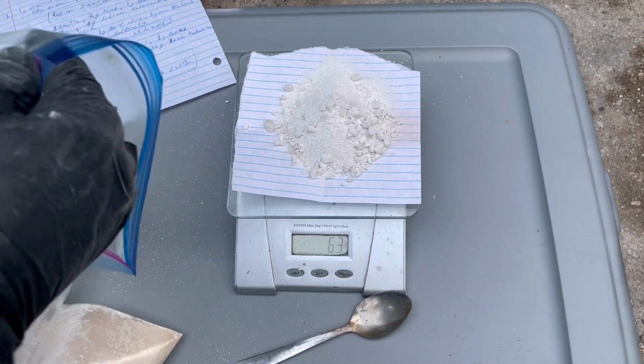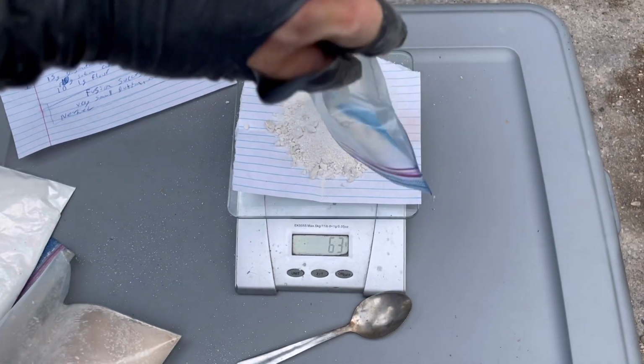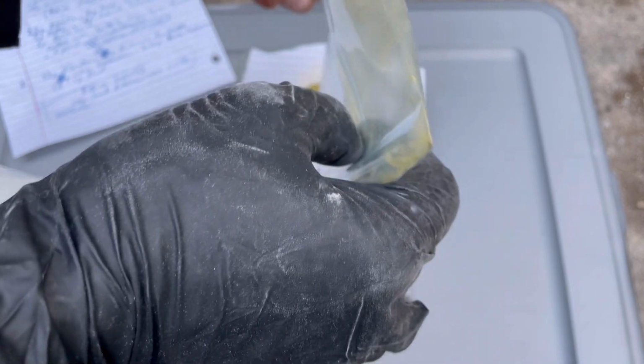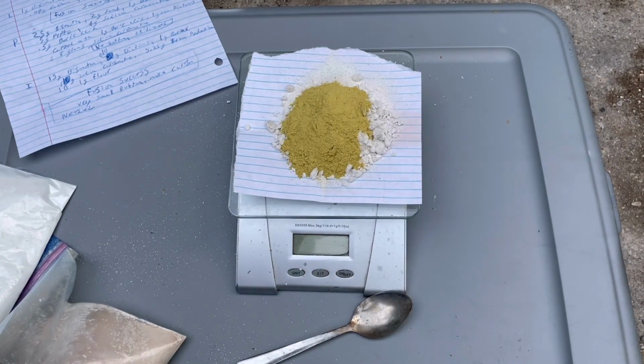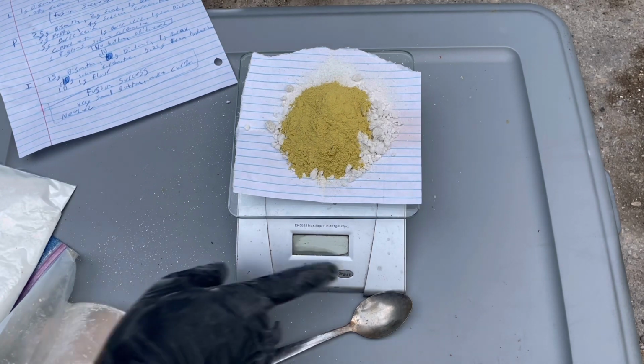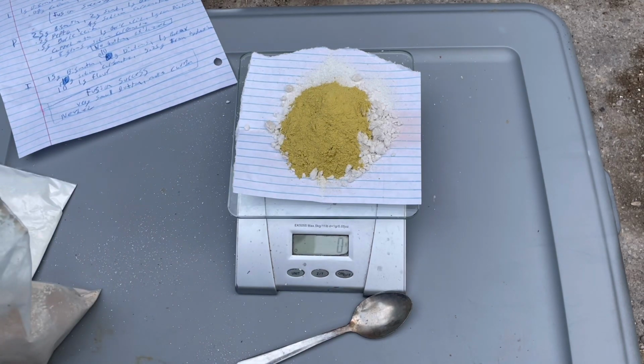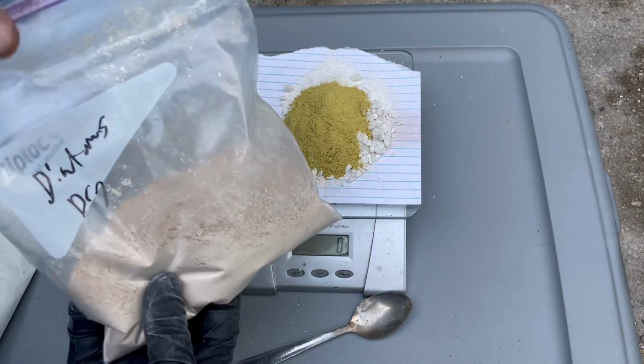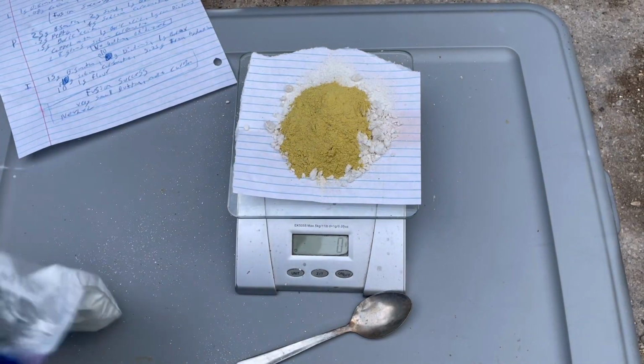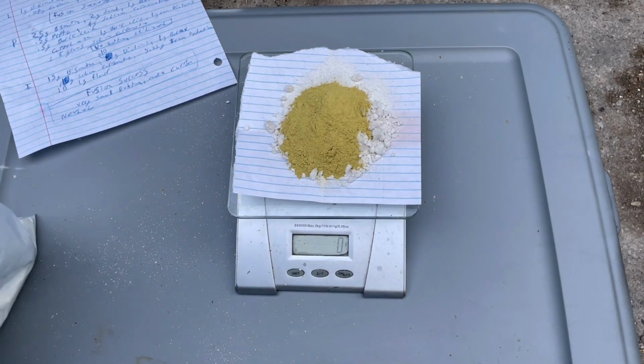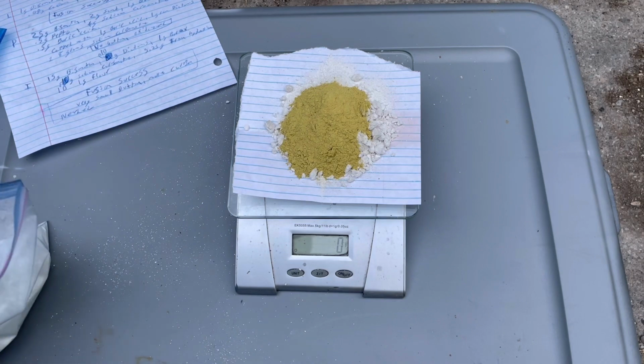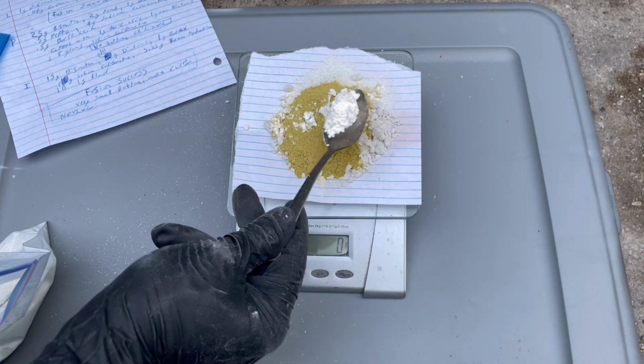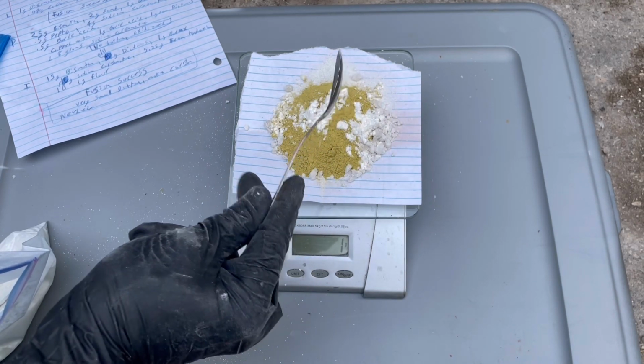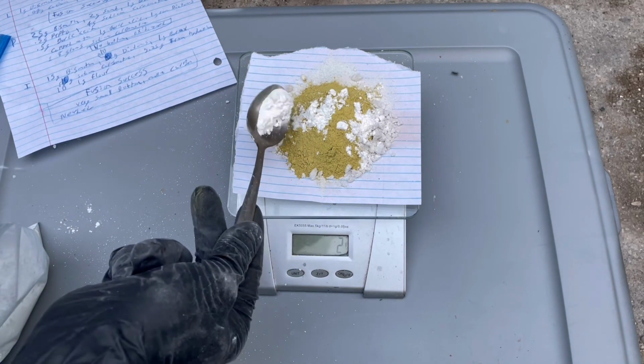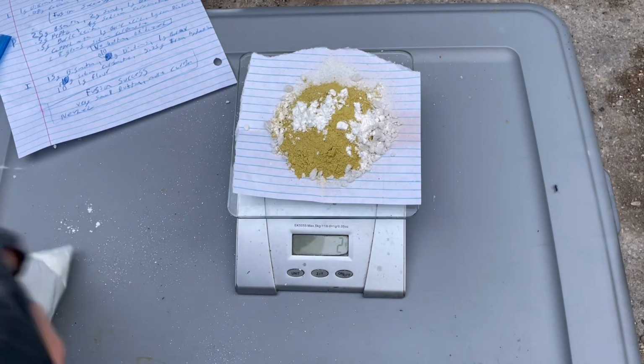Now for the bismuth that we roasted, I'm going to add all 15 grams. Oh, you little snack. Okay, not a big deal. We don't need any of the diatoms. We don't need any more silica. There's plenty there. So to reduce the bismuth, I'm going to use some cornstarch. That should take roughly 2 grams. Slight excess is fine. So there's the assay charge.